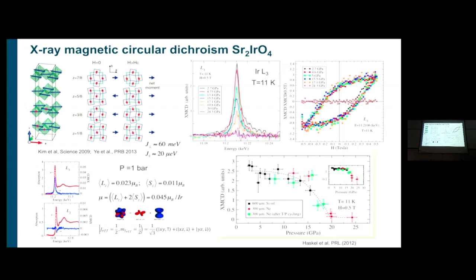But what we did is we put the sample in a pressure cell, and we say, okay, I can apply a magnetic field, induce a little bit of a moment, and then I can measure XMCD. And this is the hysteresis loop, and when you get to about 20 GPa, that hysteresis loop collapses. There is no magnetic response. So this ferromagnetic, canted antiferromagnetic order went away. It's no longer there. We don't see a magnetic response.